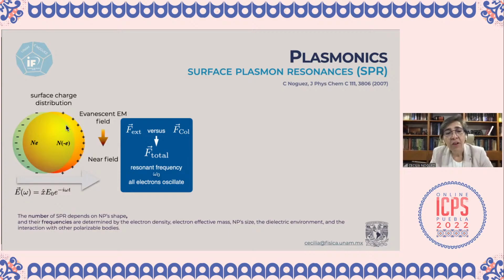This kind of surface charge distribution gives rise to an evanescent electromagnetic field, and that means that when you are close to the boundary of the particle, you have an electromagnetic field which has a large amplitude, and when you go far apart from this, the electromagnetic field goes to zero. That means that you do not have propagating modes. You have what we call a near field, not a far field. And these plasmonic systems that have these resonances are characterized by this near field electromagnetic response of the particle.